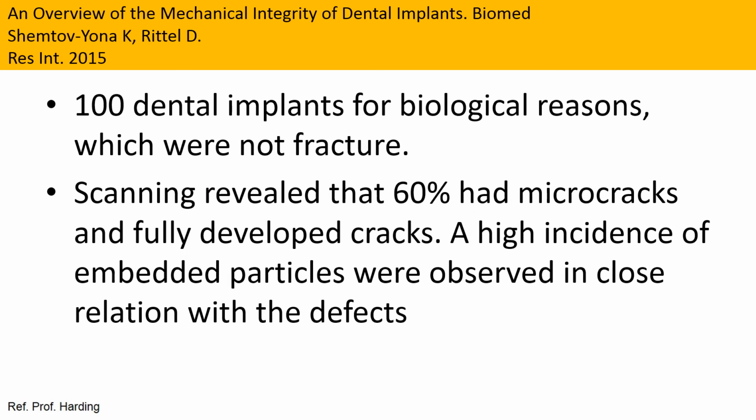This interesting article looked at 100 dental implants which were lost due to biological reasons and which were not fractured but still intact. Now the implants were subjected to scanning electron-microscopic examination, and this examination revealed that 60% had cracks and fully developed cracks. Also, a high incidence of embedded particles were observed in close relationship with these cracks or defects.